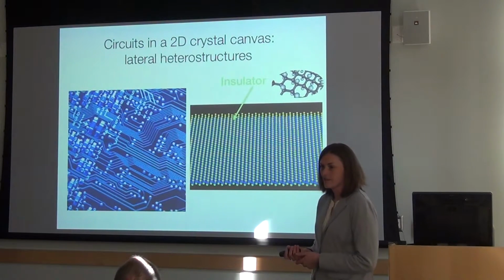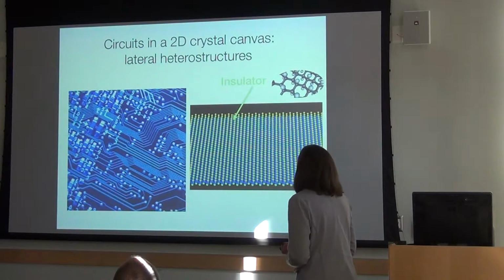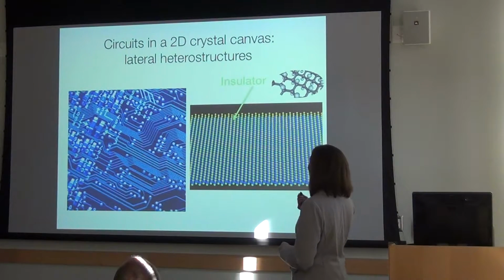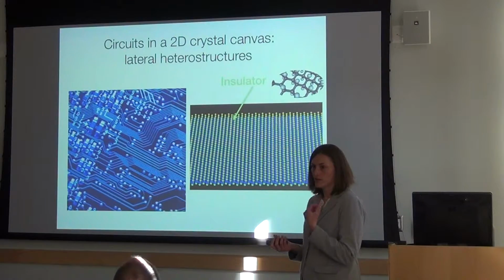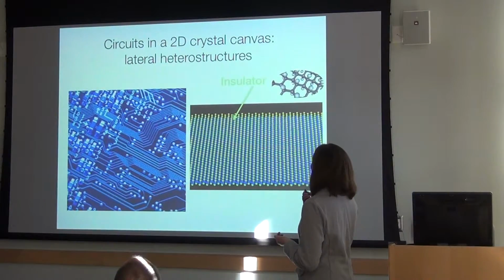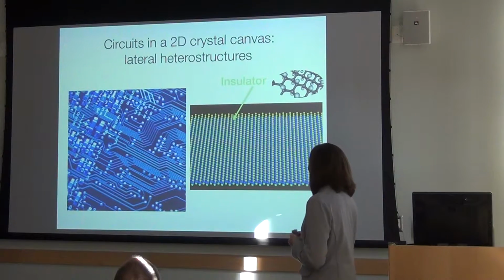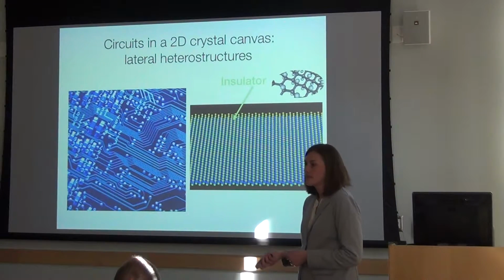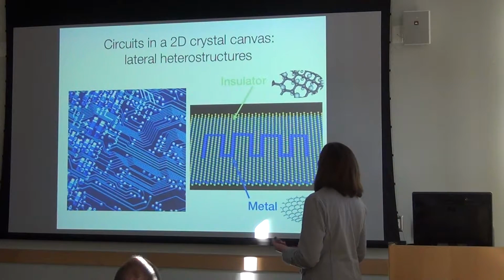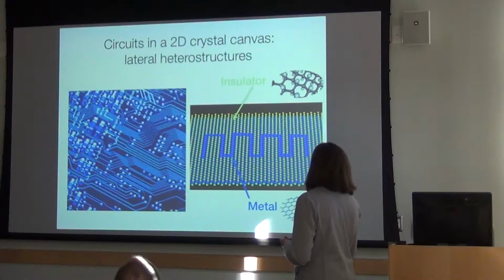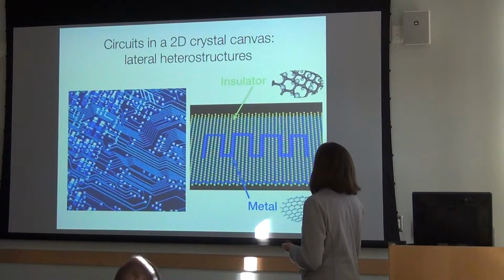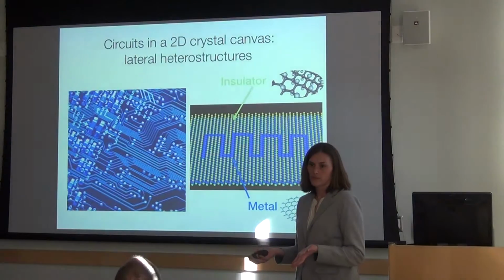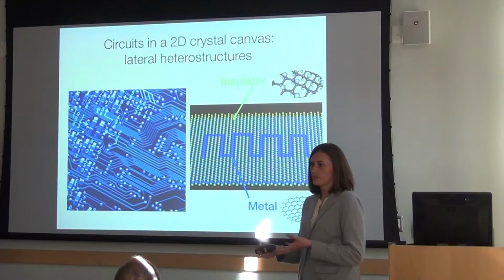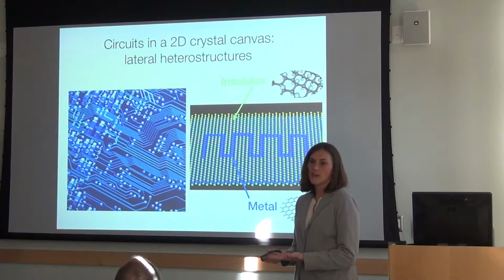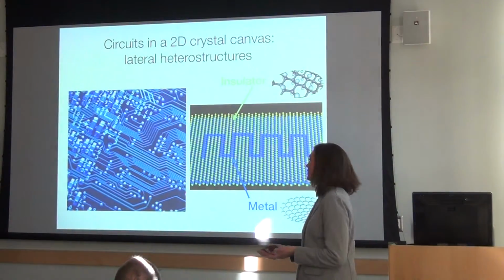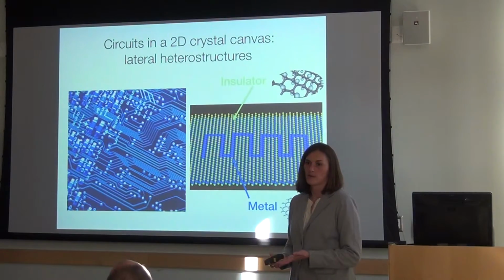So there's another opportunity here that I want to point out. Imagine that you have this graphene material with hydrogen bonded on each carbon atom, up and down. So this whole material is an insulator. Now let's say we could go in there and selectively knock off the hydrogen atoms in a pattern. If we knocked off all those hydrogen atoms, then we would have graphene, which is a metal. Because all of the properties of the material are available on the surface, you can imagine just changing the structure of these materials from the surface to change their properties in a fundamental way.